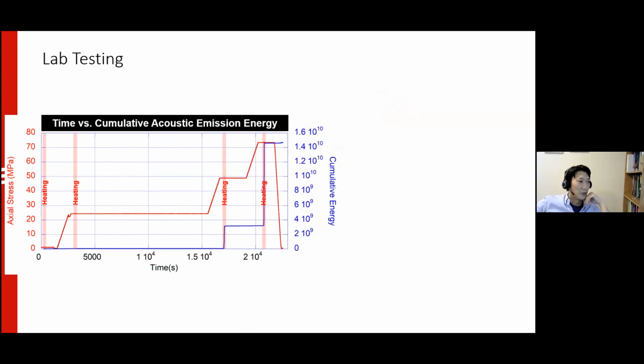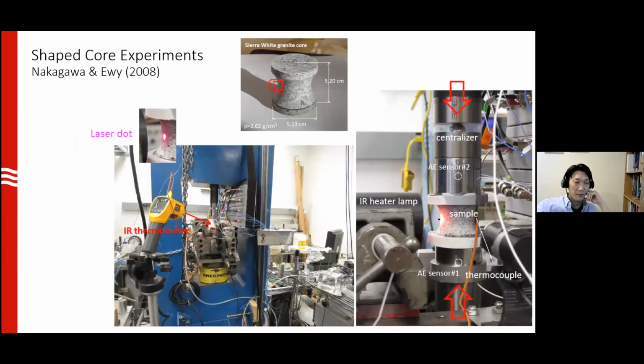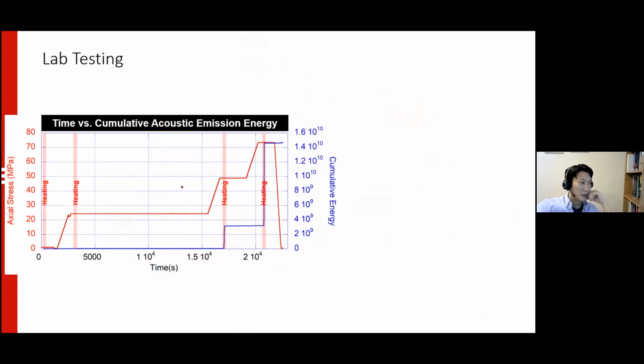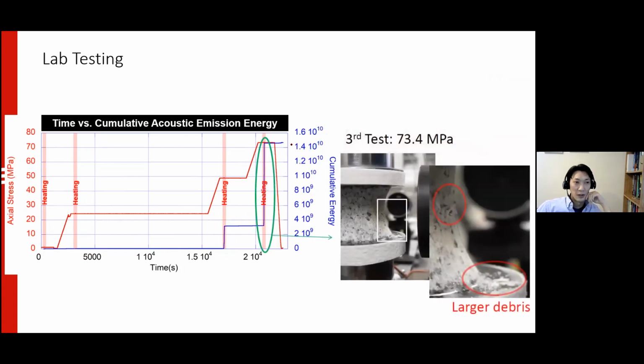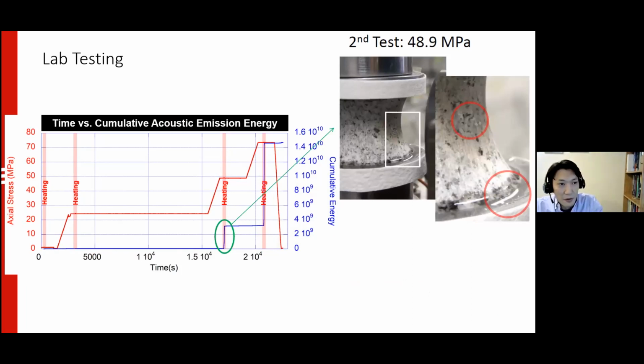This is a summary of what happens in the experiment. Red shows the axial stress that is increased in steps, and the red background is the timing when the heating by the infrared heater lamp is occurring. Increasing the axial stress is like increasing the hoop stress. When the axial stress is low, heating does not cause anything, because you don't see any acoustic emission. But once the axial stress reaches a certain level, heating does cause failure analogous to a breakout, with associated acoustic emission. In test 3, you see a simulated breakout happening and the spalling of rocks accumulating on the bottom.